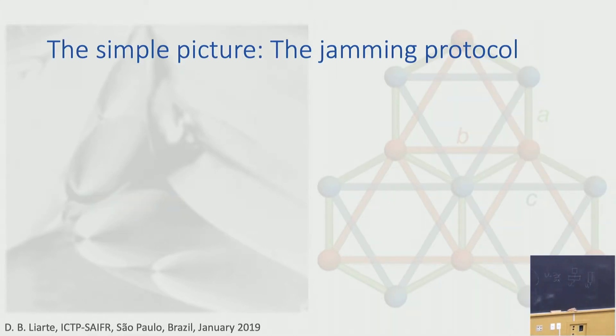So here I start with the jamming protocol, a protocol that will give rise to a jammed configuration. Just to explain what this is all about. Imagine that you have a plane, and you start with disks separated in this plane. And you start increasing the radii of the disks until they touch. And after they touch, you just stop. And you keep doing that for all of the disks in your plane. And at some point, all the disks will stop. Then you shake it a little bit, you move it a little bit, there will be some white space that they can use, and you start growing them again.